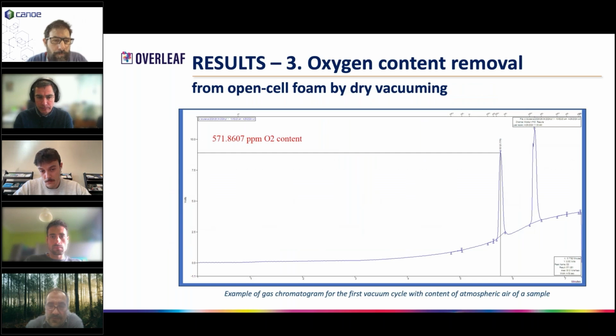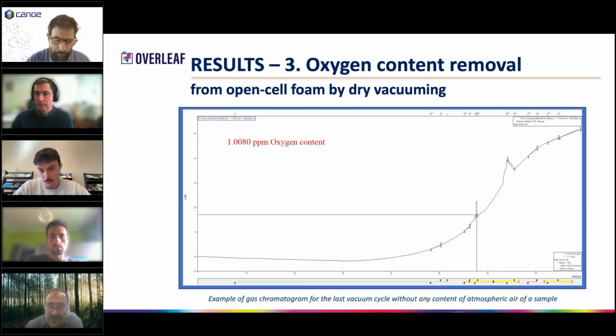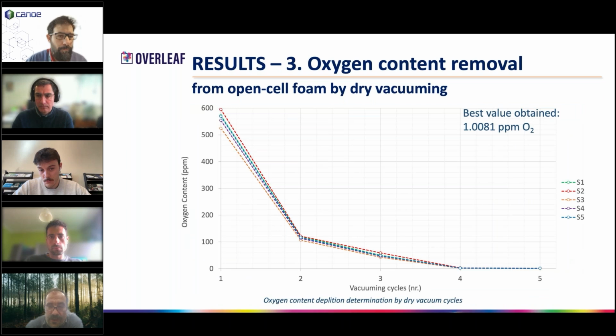We have an example of a gas chromatograph that was taken at one moment in time, and this is an image of the last gas chromatograph with a very low oxygen content. I present here the sharp evolution of oxygen content. It can be seen that in the last cycles, the evolution is not very fast. So, caution: additional measures shall be taken in order to make sure the value reaches safety